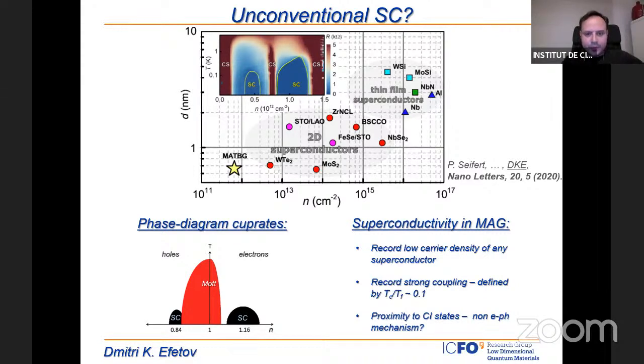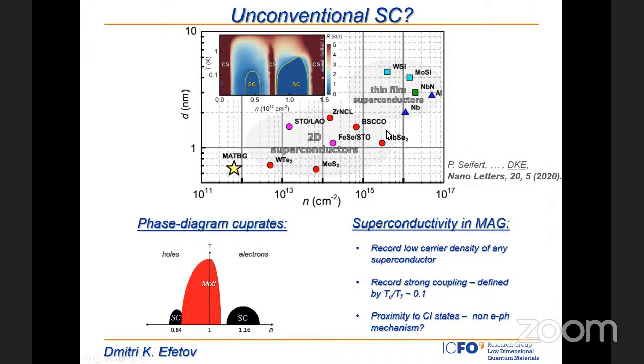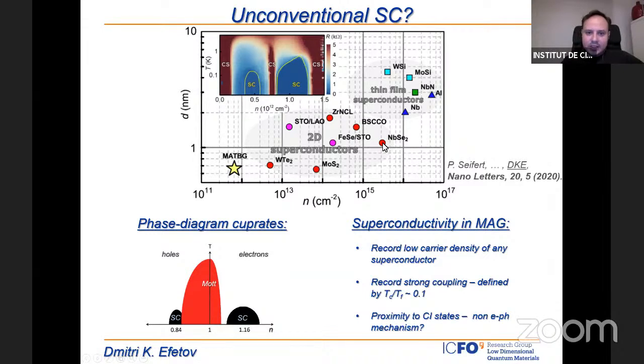So people have looked at this. If you look at this graph here, you can see that if I look at the TC of all these materials, usually the TC scales with the Fermi temperature. So it's very unusual that you get an effect like superconductivity originating from such a low electron density. The electron density is low because of the things you said, because of the moiré lattice and all the arguments you gave. The surprising thing is that you wouldn't expect a normal superconducting mechanism to necessarily give you a sizable TC under those conditions.